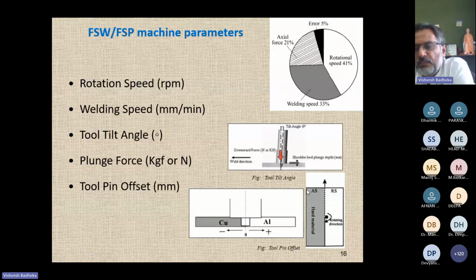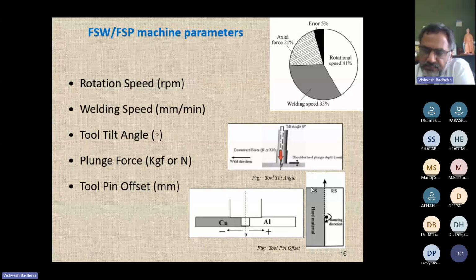So temperature is always higher on the advancing side compared to the retreating side. Around 150 degrees centigrade higher will be on the advancing side. So that's the reason you put harder material on the advancing side.